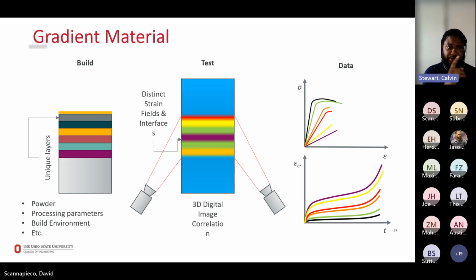If we then take that sample and do DIC on it, and if we have fiducial marks that tell us the different distinct regions, we can then, from a single sample, extract information like the tensile properties or the modulus, or even creep curves, or even, probably not fatigue, but at least creep properties from multiple materials from a single sample. Now, that really could be helpful in MGI, in new materials discovery, or in trying to figure out good processing parameters, trying to finely tune process parameters for high temperature applications.